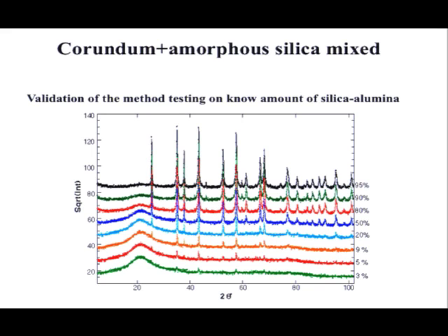Well, and the local structure, the short range order, is quite the same. So you get the electron density correct, mainly. For quantitative analysis, when you have the correct electron density, you are pretty much done, okay? You don't need more than the correct electron density scaled correctly. And the model of Lobanov gives you that, okay?